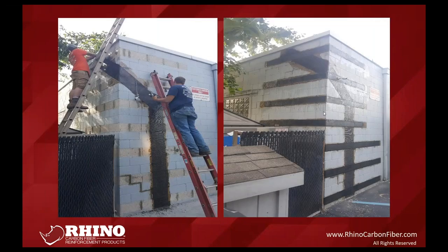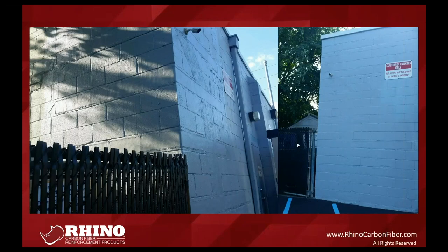This was actually an automotive mechanic shop. The corner had started to fail with pretty serious stair-step cracking. That's where you see the 12-inch wide carbon fiber utilized right here, where it wraps around the corner. There's some pretty significant stair-step cracking there. And then to further tie the corner together, they used our carbon fiber in a corner repair kit orientation. This is the after effect.